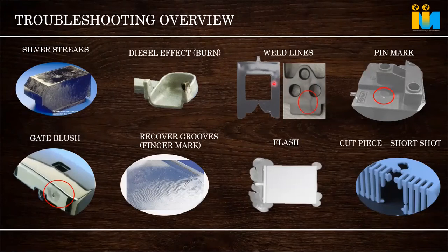Or else, second thing, we can increase the mold temperature. One thing, the mold temperature has to be as per the recommendation. If we are running polycarbonate, it is recommended at 90 to 100 degrees. If you are running at 50 degrees, then take it up to 100 degrees first of all. Then, if the gate is quite small, pressure drop in the part is quite high and the part is not getting pressure at all, so we have to increase the gate size.